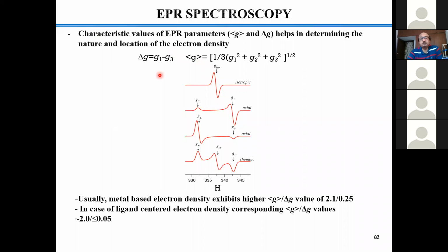And delta G is a very well defined and very effective parameter. These two are the best possible resolution based on your molecular orbital situation or your geometrical situation, right? Axial or rhombic situation. But delta G means the difference between the two extreme G values, from here to here, or here to here. This delta G, mode delta G, tells you how much metal character there is in a situation where both metal and ligand have the opportunity to carry the unpaired spin.